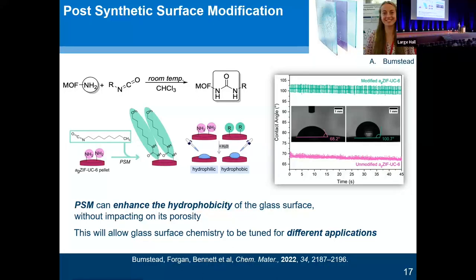So after making this amino functionalized glass on the surface, Alice did a really simple experiment. PSM has been known in MOFs through Seth Cohen and Joe Hupp and Omar Farha's work for a while now, and just stuck on a long chain alkyl group. Now that's fantastic because Alice managed to change the surface chemistry from hydrophilic, which we all know is a bit of an Achilles heel in the MOF world, to hydrophobic. So depending on what you want for your glass surface, you've got some opportunities through PSM.